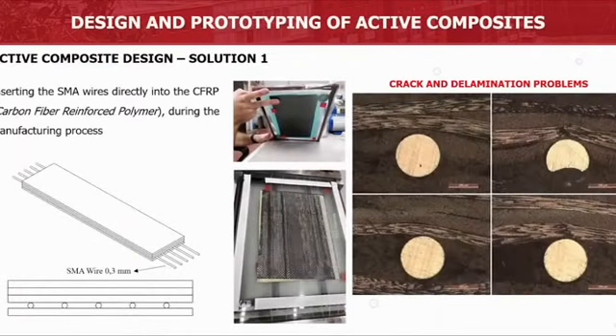Also, some prototypes were designed. Solution 1 is to insert the SMA wire directly during the lamination process of the carbon fiber reinforced polymer, but this showed very bad performance. In fact, some cracks in the lamination occurred after some actuation cycles.